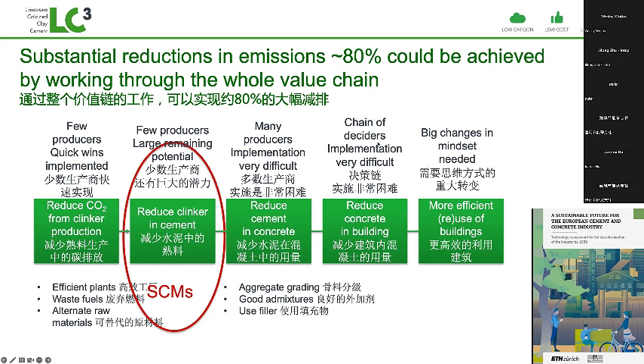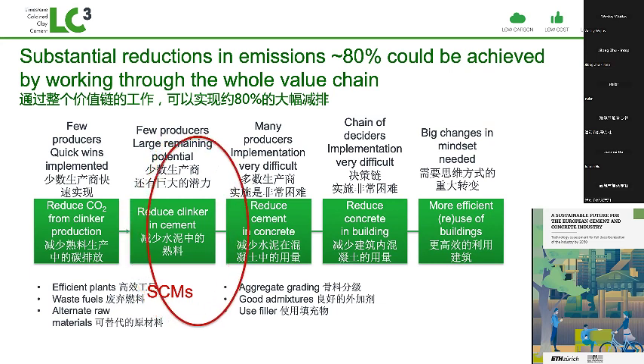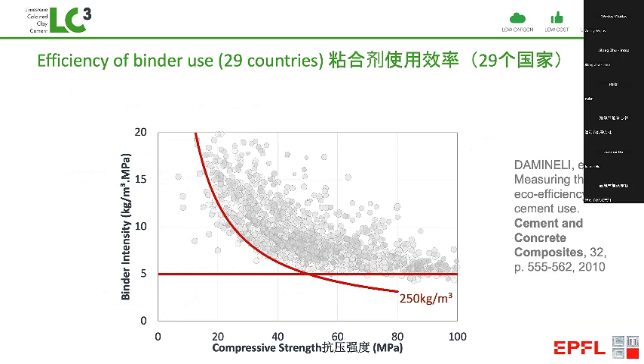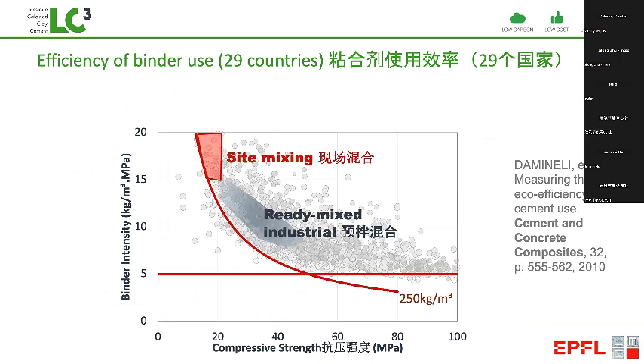For example, if we look at cement in concrete, we see that around the world there is tremendous dispersion. This concrete here uses 3 times as much cement as this one here. 3 times as much cement is 3 times as much CO2. So we can improve the efficiency of concrete by moving from site mixing to industrial production in ready-mix plants. This is an important technology in some parts of the world where much material is still mixed on site, but we really don't want to go in the reverse direction. And this is what is happening with technologies like 3D printing, which are taking out the large aggregates. This increases the cement content and vastly increases CO2 emissions. So we really must be intelligent about solutions that can take us in the right direction of reducing CO2.